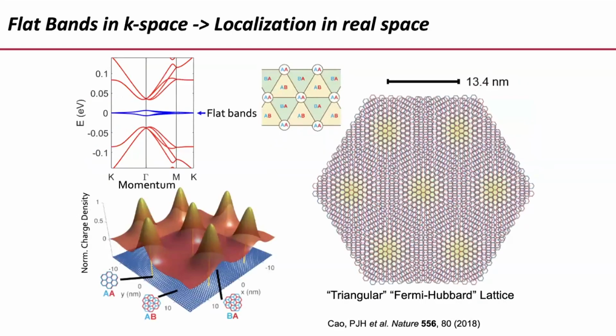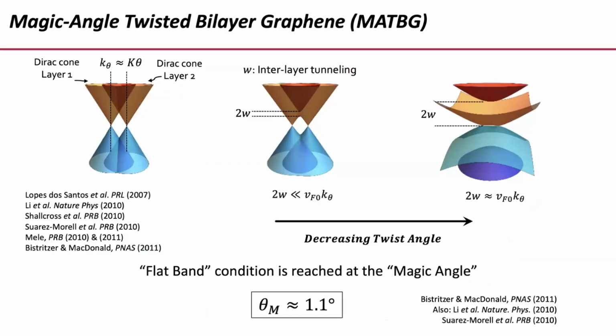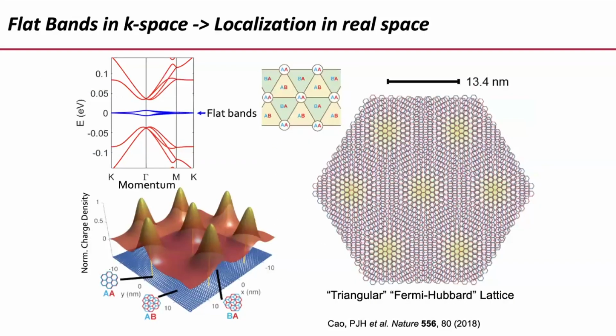If you do an actual calculation nowadays, including also some extra relaxation, and so this was a cartoon here, this is an actual calculation. These are the flat bands. These are the other remote Moiré bands. Okay? If you look at where those electrons like to sit in real space, when you put your chemical potential in these flat bands, they like to sit in certain regions of AA stacking, and they like it less on the regions of AB and BA stacking.